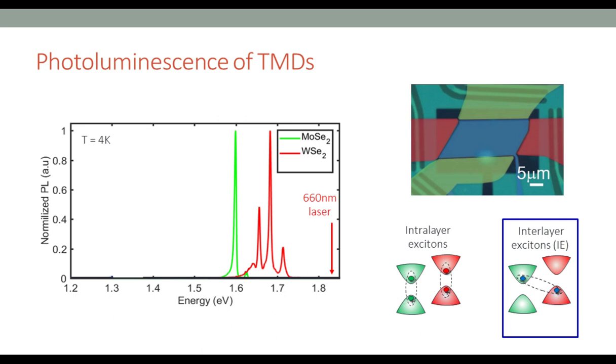So these are the exciton, trion, and some defect peaks for the WSe2, and for the MoSe2, you can see that there's a dimmer MoSe2 exciton with a very bright MoSe2 trion. This is essentially the photoluminescence spectra for the two materials individually, but when you combine the two, we actually find interlayer excitons, which are at much lower energy. Since the two layers form a type 2 band alignment, their effective band gap is much smaller, around 1.3 eV, which is where we see our interlayer exciton peak.